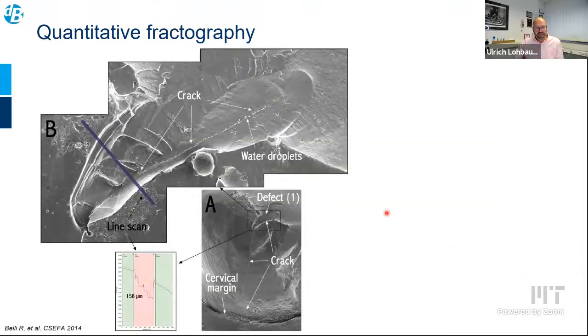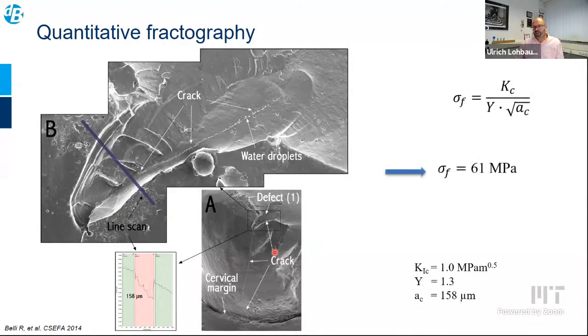And then we can go further. This is an example of what we did on a fractured crown. It's just the fracture origin shown. This is here, and we measured the fracture size. And from the fracture size, I won't say calculate, but estimate the level of stress that was necessary to drive the crack through the material.